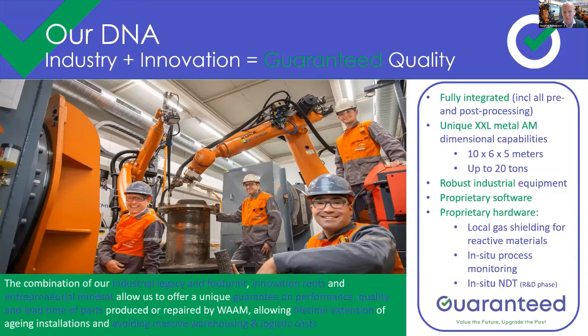At the moment, we have a production facility which is located in Ghent, in Belgium, which is fully operational, which has unique capabilities in terms of dimensions. As you see on the slide, we have the possibility to produce parts up to 10 by 6 by 5 meters, and we're able to manipulate components up to a total weight of 20 tons. And we're doing that for a variety of different materials, from carbon steel, stainless steels, nickel-based alloys, aluminium and titanium, because we're also using different welding processes in our operations.